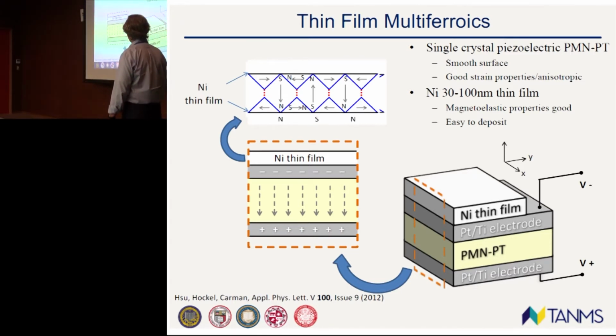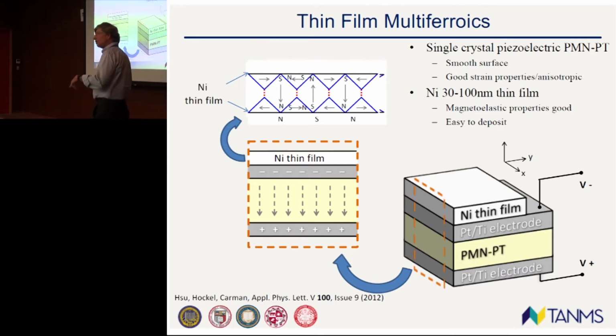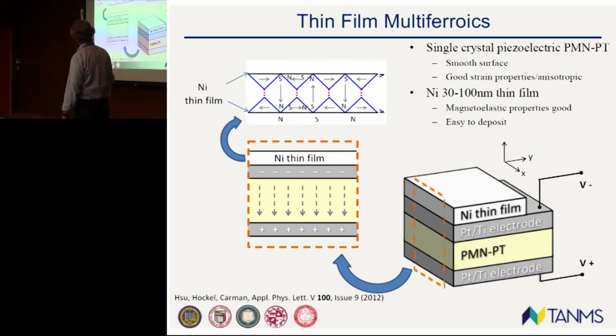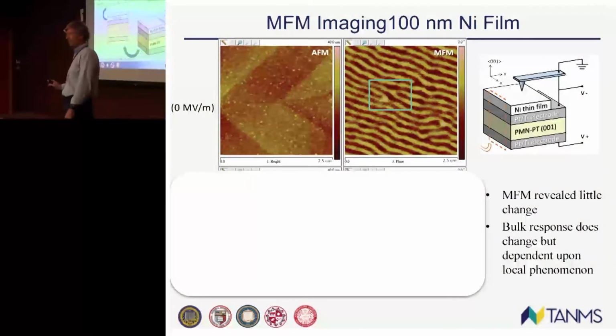And what we're going to do is we're going to take this bulk piezo, we're going to apply an electric field, and we're going to try to stretch that nickel film. But let's start off with a hypothesis, okay? So if we look at the side view of this nickel film, look, it's multi-domain state here. And what you should see if you were a little ant, or let's say you had a magnetic force microscope image, as you walk from left to right, you would see this little south pole exiting the film. You would see a little north pole here, and you will see a south pole here. What we want to do is apply an electric field that stretches this film. So if you watch this here, we want to move those domain walls and actually close that path off so that we actually prevent it from exiting the material. So we would have controlled magnetism in the small scale now.